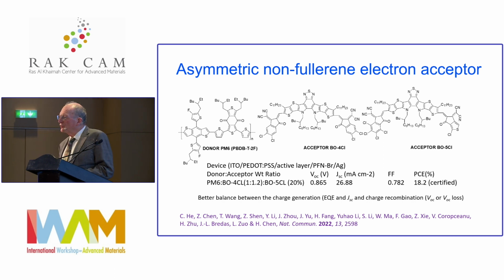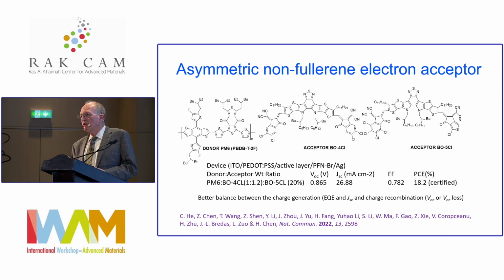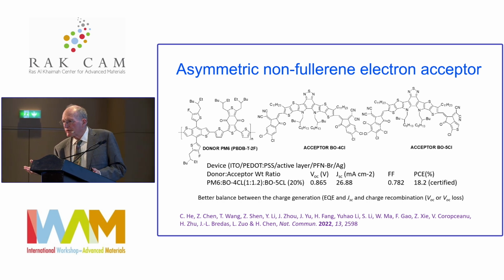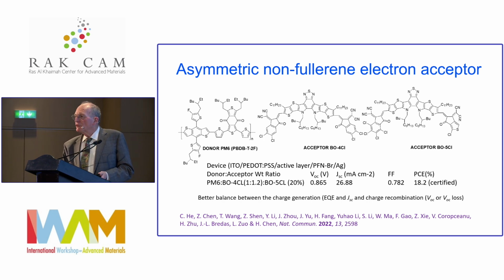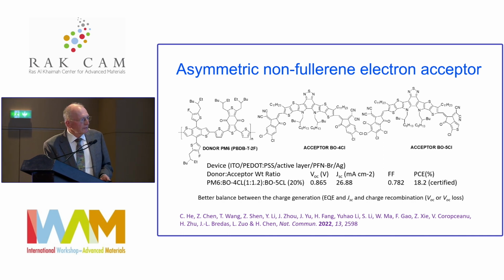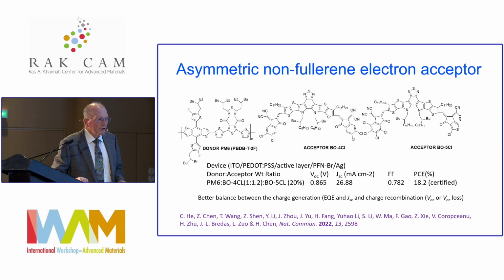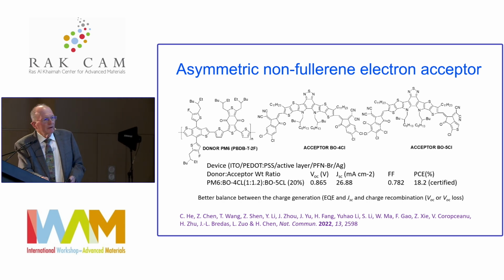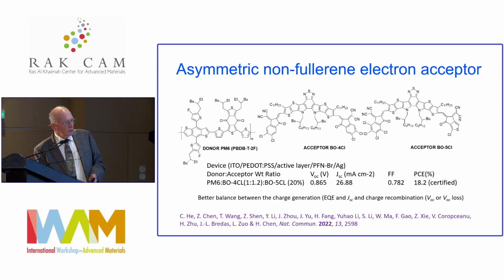And I should say that the explanations that I'm giving you emerged from the investigators having done a range of structural and spectroscopic studies to back up their conclusion. The kinds of things one can do is fast spectroscopy, which gets you a lot of information on lifetimes of excited states, and then various types of wide-angle scattering and other AFM, surface roughness studies, and so on, to understand morphology. So that's how they come to the conclusion that by having this blend of an unsymmetrical acceptor, the balance between charge generation, which influences external quantum efficiency and short circuit current, and charge recombination was better, influencing the open circuit voltage or the loss of the open circuit voltage.